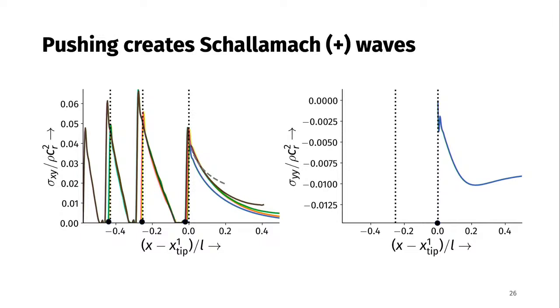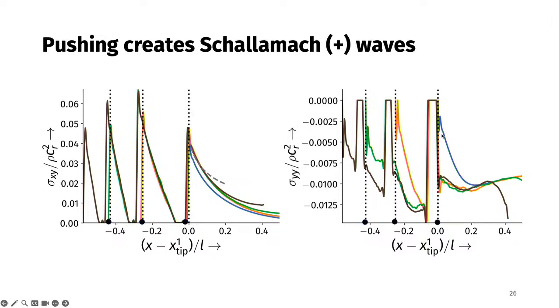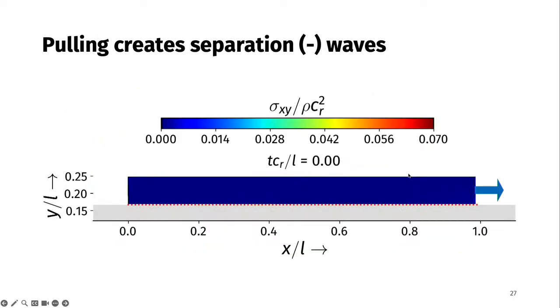We can look at sigma yy, which becomes much more interesting. This also seems to be singular. Again, this is a finite lattice, so you can't say if it goes to infinity or not. It won't, because of the finite distance between these bonds and the forces in the bonds. And again, if you look at it in the co-moving frame, the stress falls off. This region is 0 basically because it's behind the wave where it's detached, just like here. The stress initially was very high when the first wave nucleated, but after that the normal stress is reasonably low, continues to be low, and the same thing happens with subsequent waves as well, right?